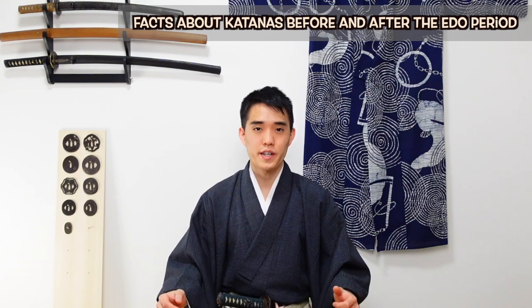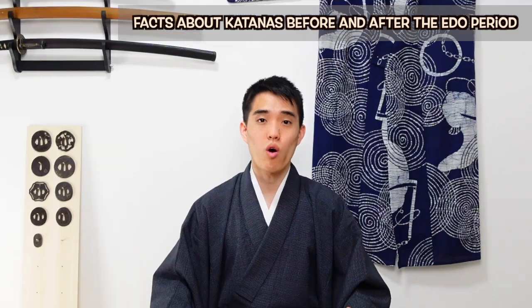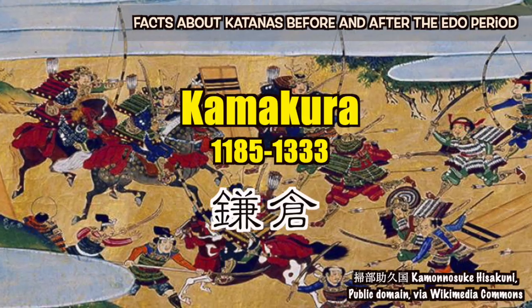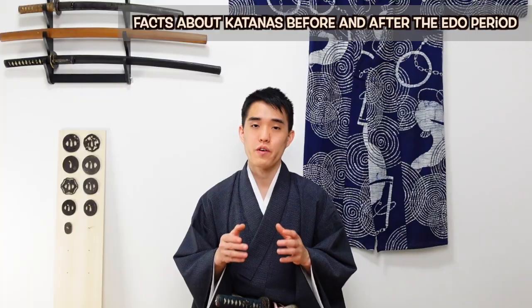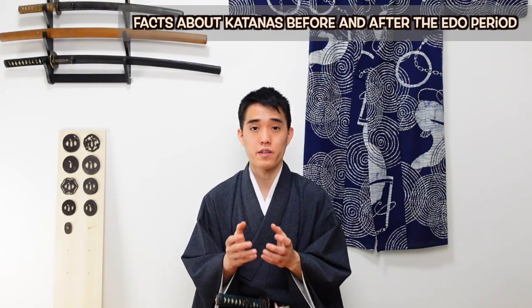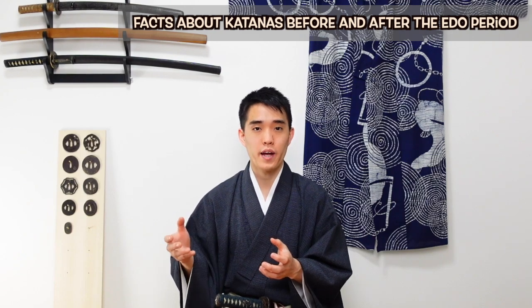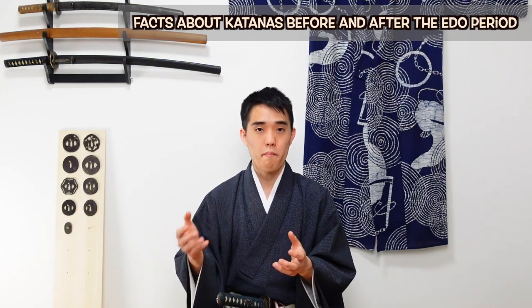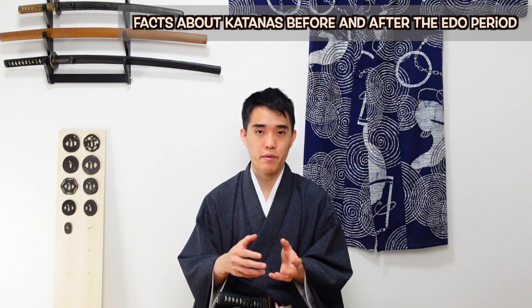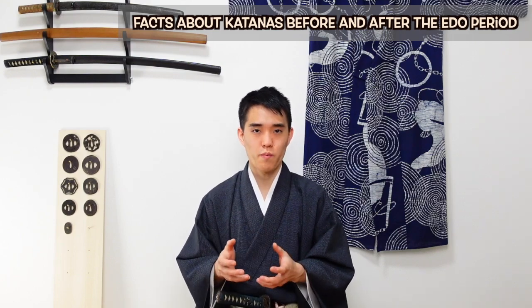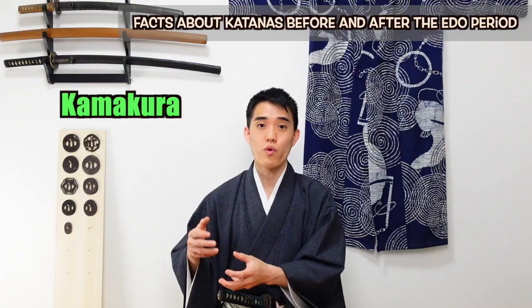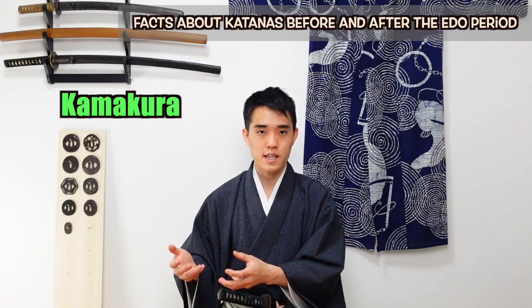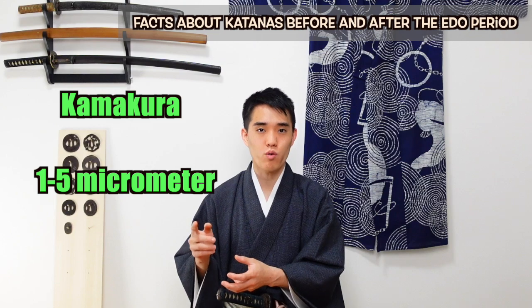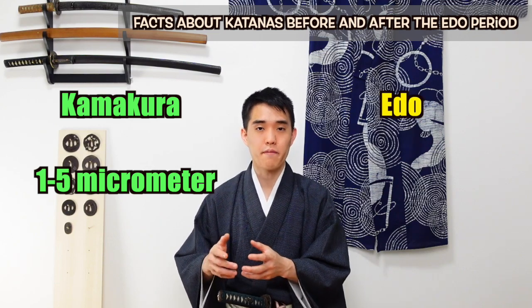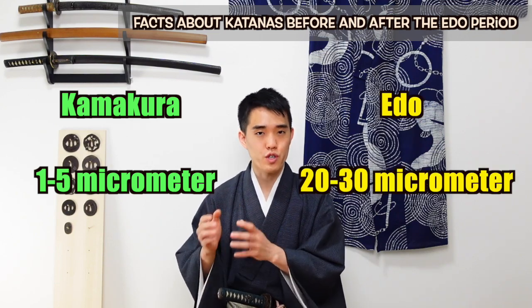A Japanese metallurgist named Masahiro Kitada once conducted a study on the crystal grains of 30 different katanas dating from the Kamakura to the Edo period. He found that among 30 randomly collected swords, those made in the Edo period had larger crystal grain size compared to the ones made in earlier periods. The difference was especially noticeable in the grain size near the blade edge, with Kamakura period swords having a grain size of around 1 to 5 micrometers, while Edo period swords had grain sizes of around 20 to 30 micrometers.